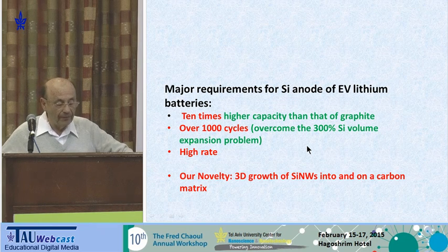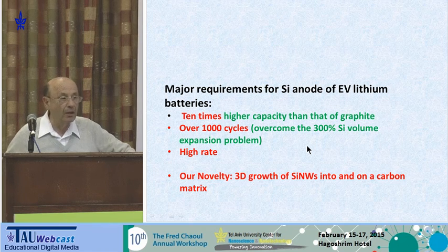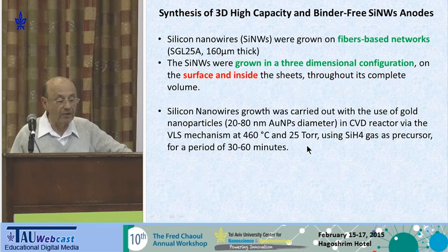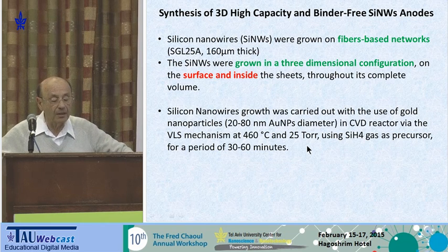Then we like to have high rate, and our novelty is the growth of three-dimensional silicon nanowires into and on the top of carbon matrix. Previous research in this field just grew a silicon forest on a flat substrate, but we did it all over the volume of the carbon matrix. So we synthesize 3D high-capacity binder-free silicon nanowires, and we took a carbon paper, which consists of a fiber-based network, and we grow the silicon nanowires inside and outside this matrix. Therefore, you get quite high capacity.